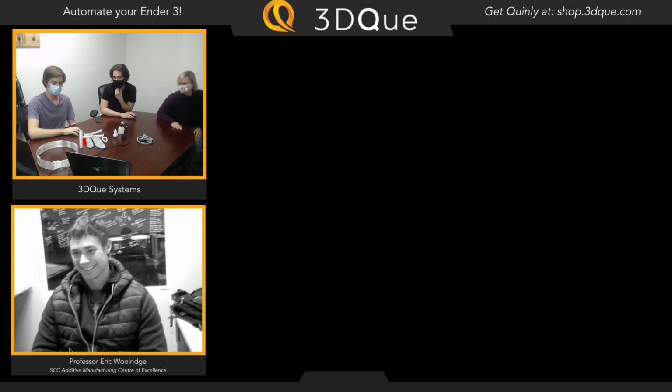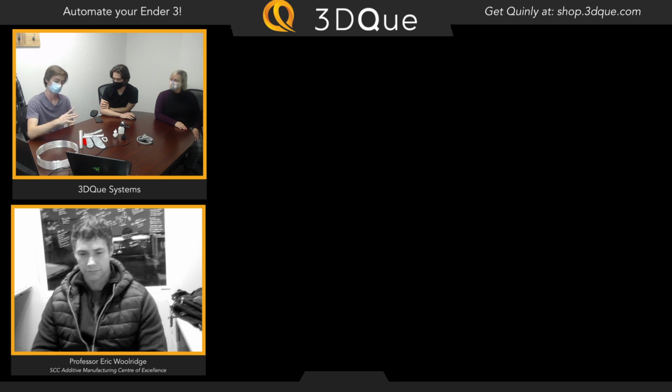Yeah. And so what I found is when printing nylons, there will be a small section right in the middle of the part that keeps stuck. And then the edges will peel off, and I'm sure having an enclosure would help with that. But yeah, the first layer goes down great. Second layer goes down great on top of it. It's just when there's 10 layers and they're all contracting at different rates, that's when the warping kind of sets in.